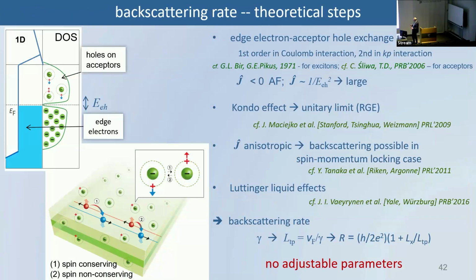And actually to calculate that quantitatively, you have to calculate exchange coupling between these edge electrons and this acceptor states. You have to calculate Kondo effect because actually this exchange coupling is very large, because this exchange coupling is inversely proportional to the square of the energy difference between these holes and electron and boundary states at the Fermi energy. This is a few millieV. So this coupling between electrons and holes is very large. And this gives rise to Kondo effect.